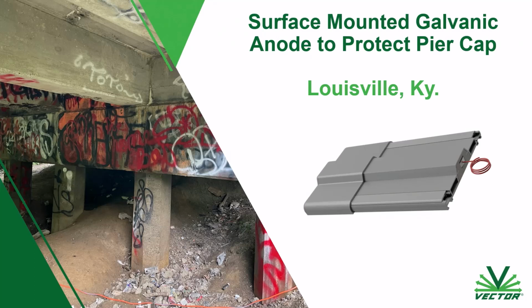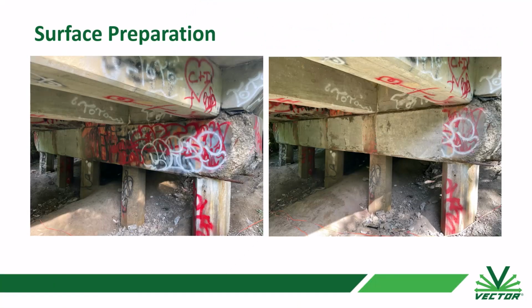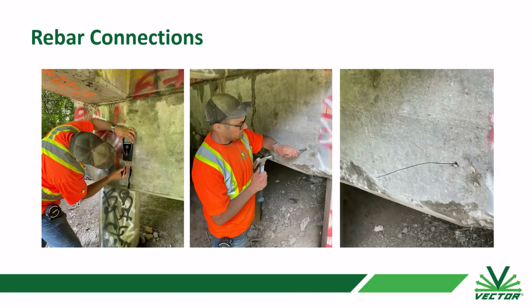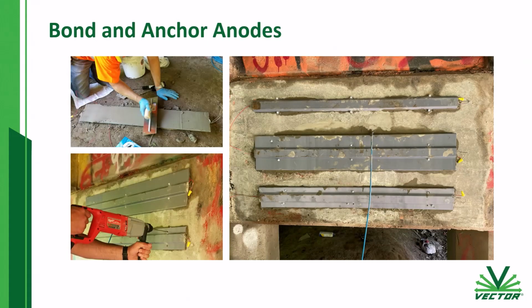So one thing it does is it eliminates a lot of the drilling that you saw with doing the drill holes for those two-stage anodes. You basically still need to make a reinforcing steel connection, but you'll eliminate a lot of the drilling to embed anodes into sound concrete. So this is a little section that we did, just some minor surface preparation just to remove the graffiti and some surface laitance on the concrete. Like I said, you need to make the reinforcing steel connections.